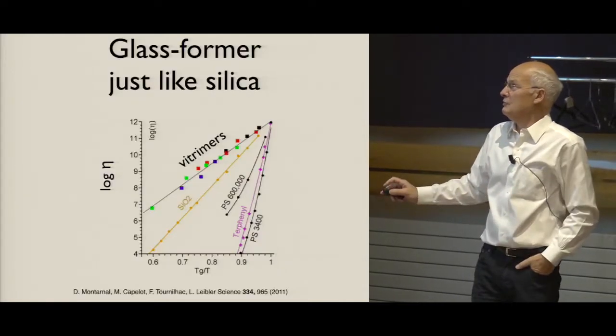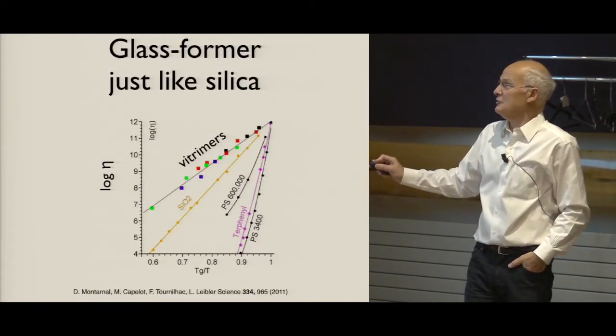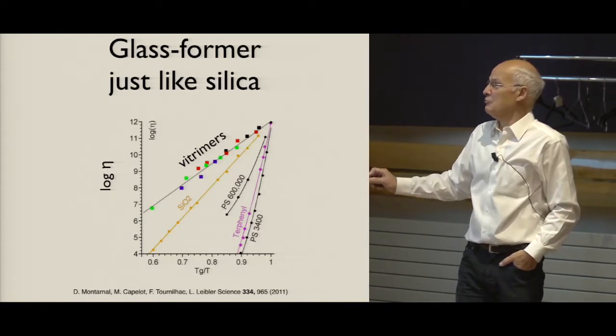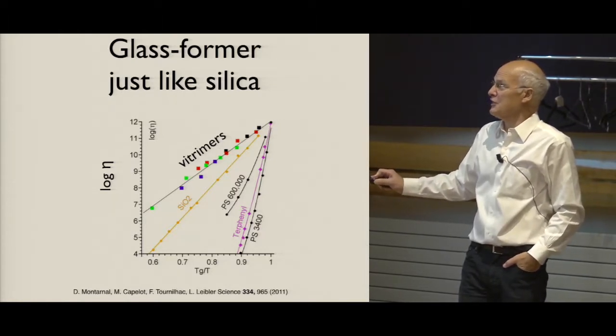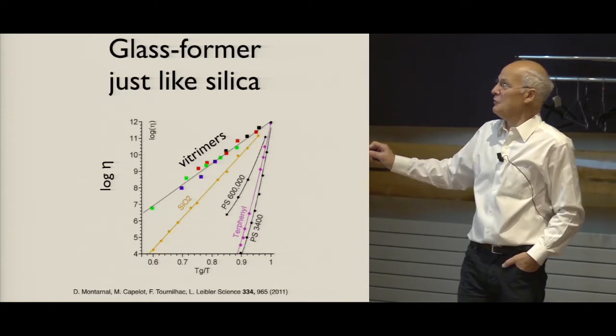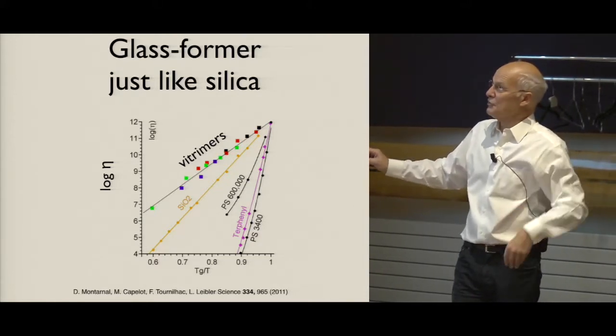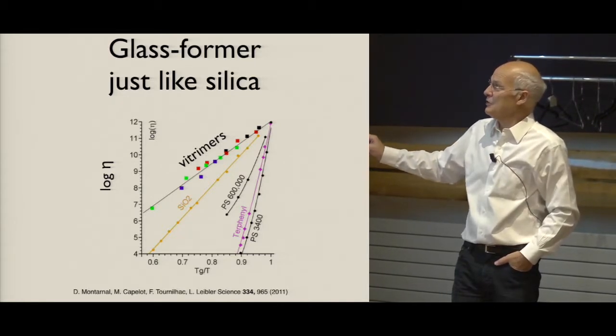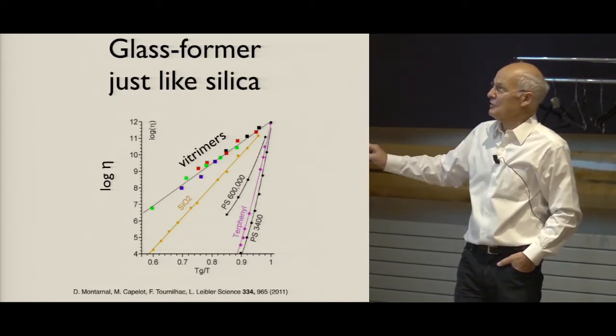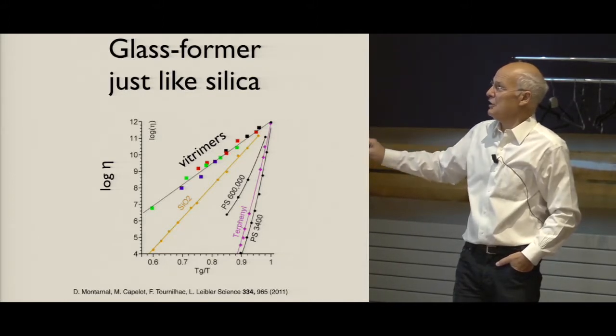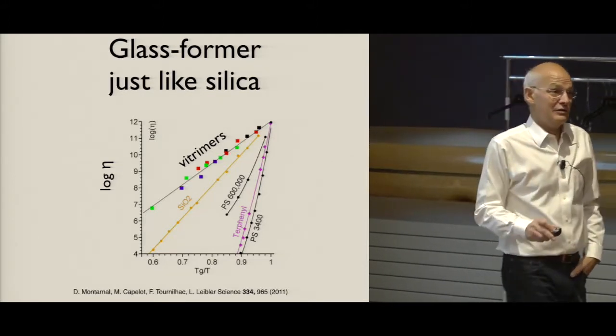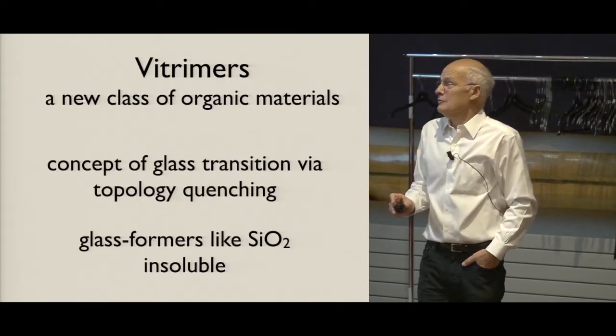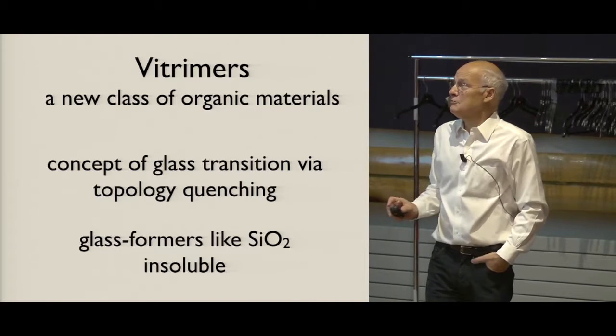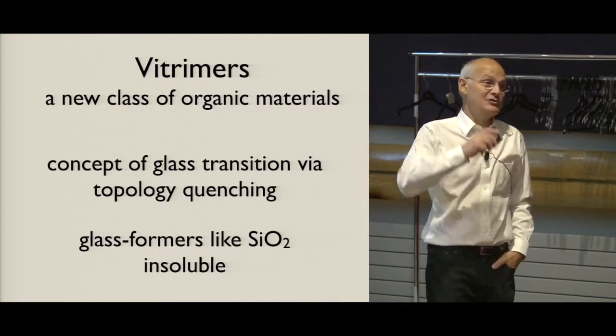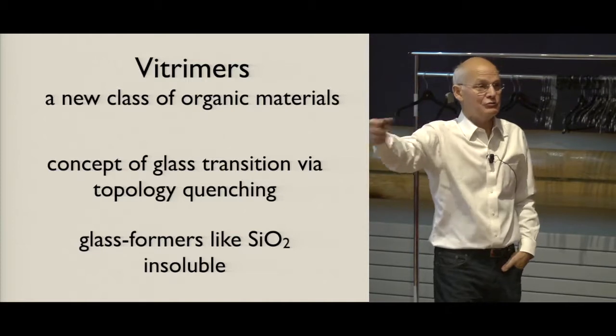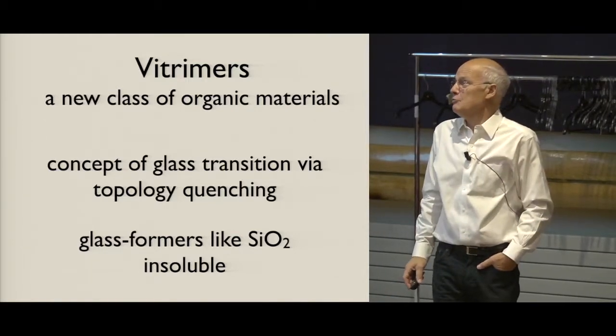So it's malleable, and you can calculate the viscosity. And then when you plot the logarithm of viscosity as a function of 1 over temperature in this Arrhenius plot, you find that the epoxy vitrimers, and the other vitrimers which we made since then, behave just like silica. They obey this Arrhenius law, and they behave very differently than all other plastics. So clearly vitrimers are a new class of organic materials which combine this aptitude to flow and be insoluble.